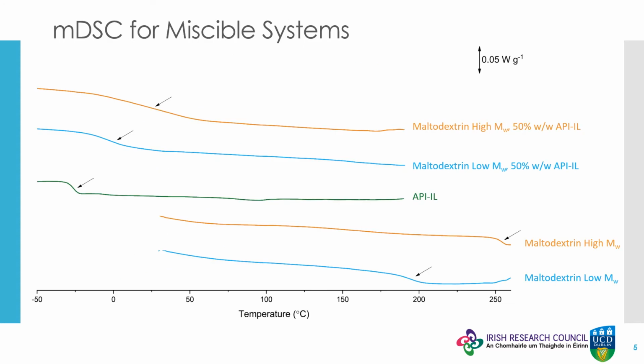Modulated DSC shows that the API-IL is miscible with maltodextrin from the single broad glass transition temperatures that lie between those of the pure components, with points taken as the TGs shown by arrows in the graphic. For this API-IL, the TG is the same as the melting point, and as the solid product was recovered from the spray dry, this shows that it is possible to solidify an exceptionally low melting point drug by an appropriate selection of high TG polymers.